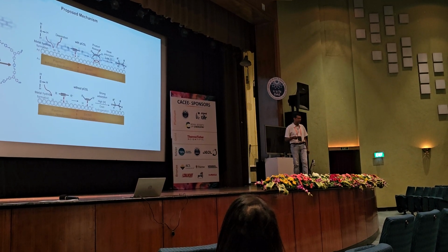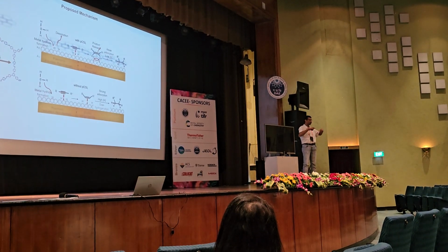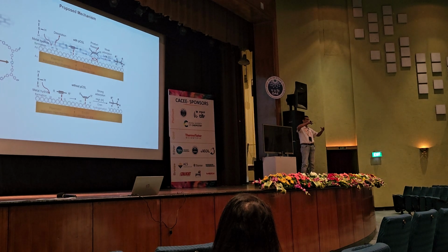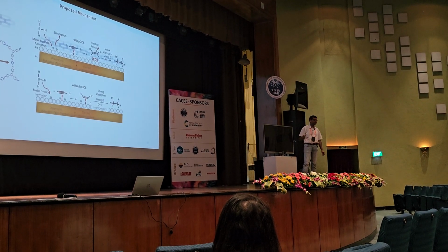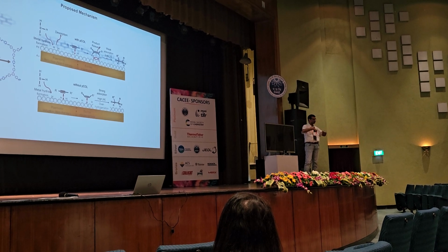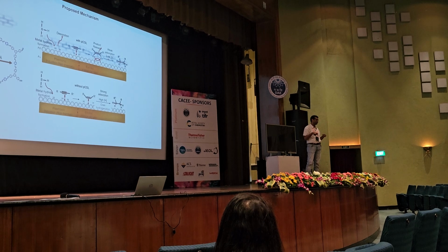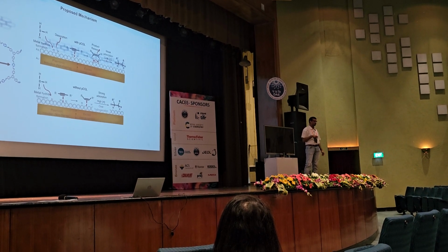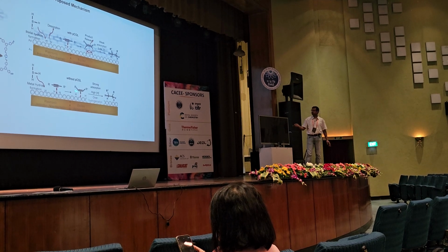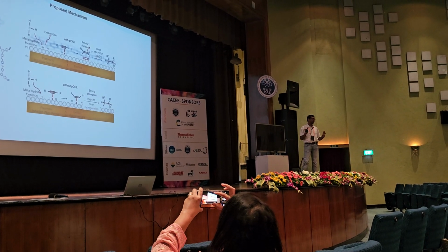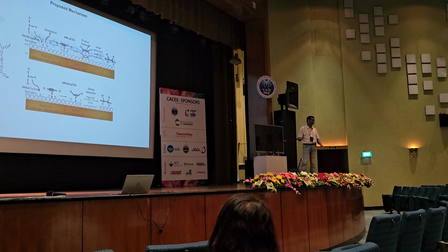So in heterogeneous catalysis, the reaction actually proceeds through adsorption. Unlike homogeneous catalysis, where you have the facility to rotate the bond as the intermediate forms, on a 2D surface it always goes through the cis addition pathway. That's the basic mechanism, and it has been known for a long time. So we have made no effort to get this cis. The polymer layer has no influence on that; any naked metal surface can do that.